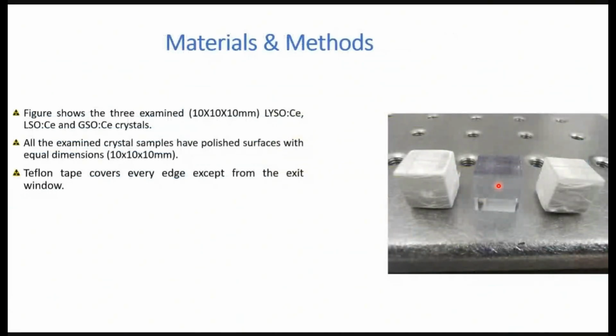In our experiments, the scintillator crystals have polished surfaces. All surfaces are polished and have equal dimensions for comparison purposes. The dimensions are 10 by 10 by 10 millimeters. And for the experiments, we wrap the crystals with Teflon tape, all surfaces except one, in order to allow the light produced upon excitation to escape from the material.